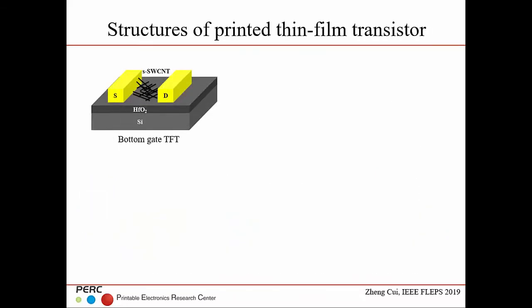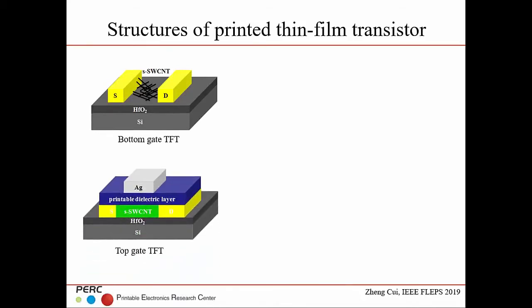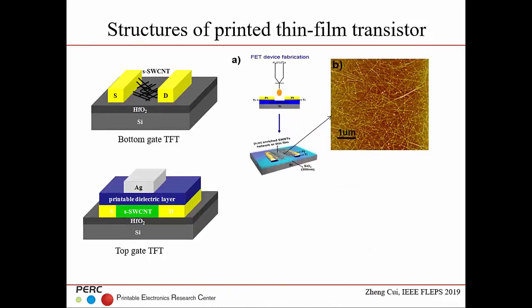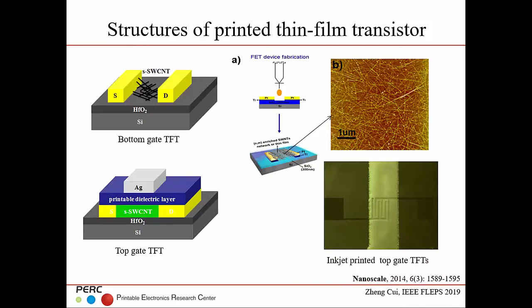Then we use inkjet printing to make the transistor, mostly printing the carbon nanotube. This is the bottom gate, this is the top gate, and that's how it's done. We make the electrode, then we use inkjet printing to deposit the carbon nanotube between the source and drain, and that's the randomly distributed carbon nanotube network. And this is the electrode that you have. This is the gate, and this source drain is the single carbon nanotube transistor.